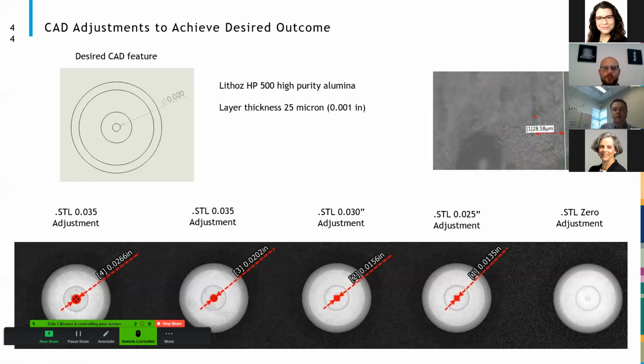During the same printing, we also verified that the layer thickness was within specification from the printer. As you can see here, we have a 25 micron, or 1/1000th of an inch, program setting, and we achieved 28 microns, and the 3 microns would be negligible based on the measurement criteria.